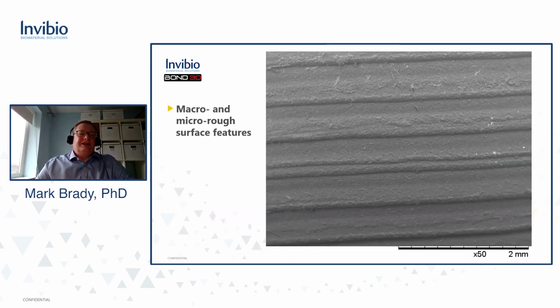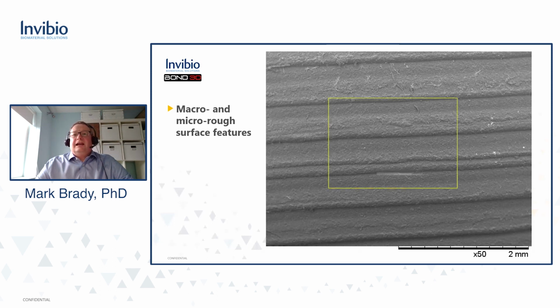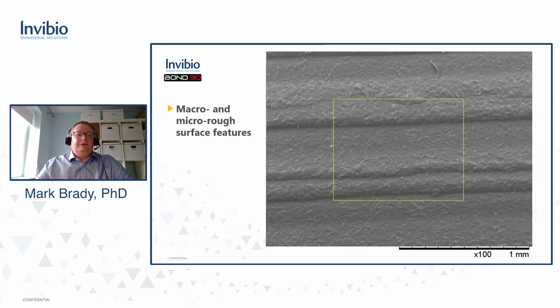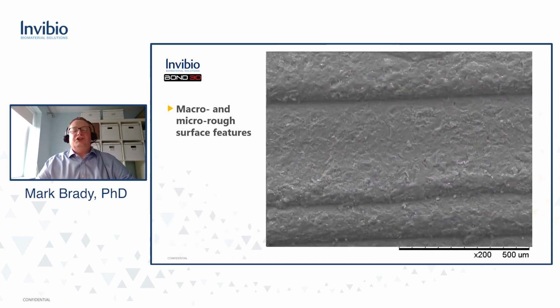And when we start to look at the printed surface under scanning electron microscopy, we could also start to see some of the macro and then some of the micro topography. So offering a different surface to machined or injection molded PEEK that might conceivably play a role in osteoblast adhesion and bony integration.